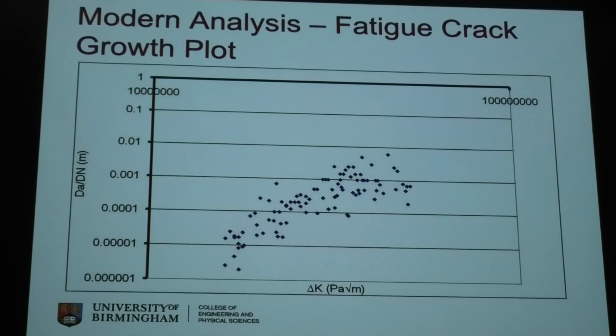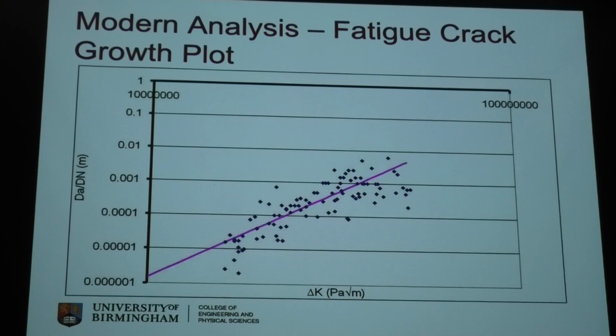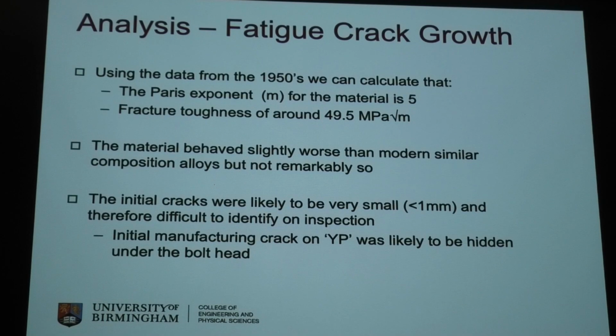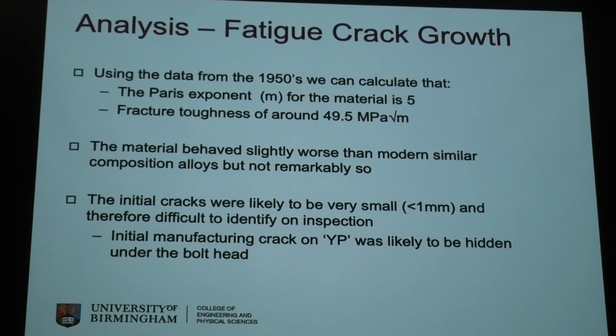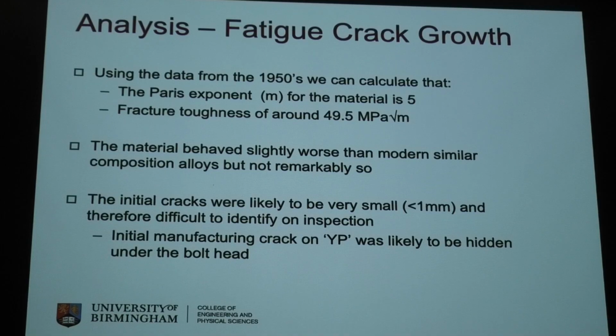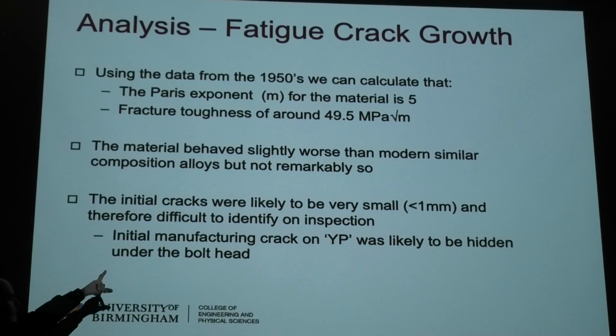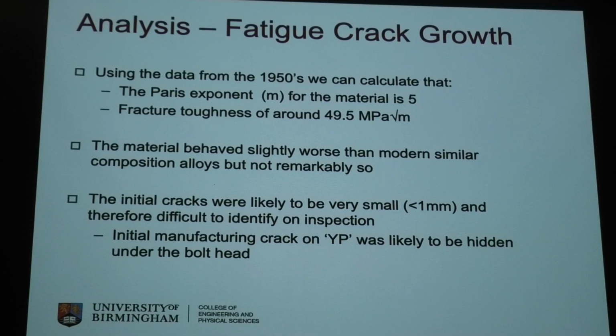But that's all the data that I've managed to glean from all of the reports and plot onto one graph. And you've got this rough kind of line that goes through there, and if you plot that line through there, you can say how the material behaves. And using all this data, plugging it all back in, the material probably behaves slightly worse than a 2000 series alloy, but not markedly so. The initial cracks were probably less than a millimetre in size and difficult to identify on any inspection. And it was probably the case that if we look at all those small crack lengths, they were probably under all the rivet heads. By the time you punched a rivet hole in there and popped the rivet in, you've probably given yourself a millimetre, and you've put the rivet head on top of it, you can't find it.